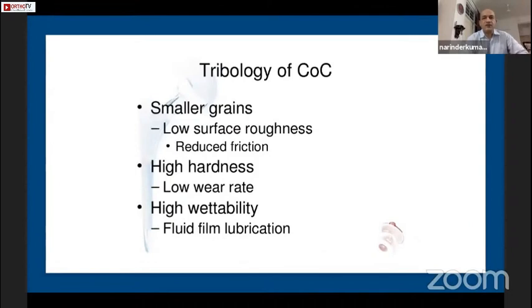But one must understand the tribology of ceramic on ceramic, that the smaller grains have led to a lower surface roughness, leading to reduced friction. High hardness of this delta ceramic has led to low wear rates, and high wettability of the same ceramic has led to fluid film lubrication.